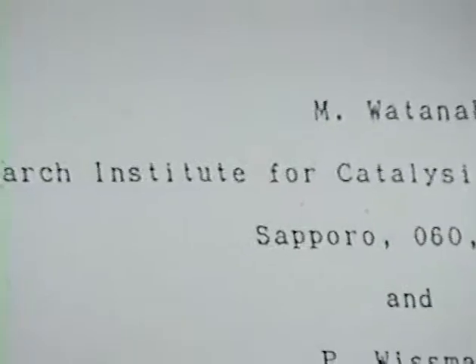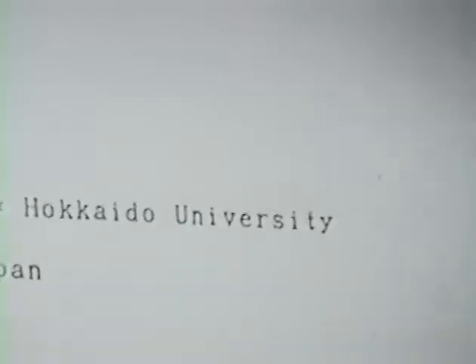We often introduce hydrogen gas onto the iron catalyst, for instance, at about 400 C. According to the thermal desorption experiment, the absorbed hydrogen is unstable, and most of the hydrogen is desorbed. Under such a condition, we introduce the hydrogen onto the catalyst surface. However, we can obtain a nice Fischer-Tropsch reaction without absorbed hydrogen? No, I don't think so. There is some absorbed hydrogen on the surface.